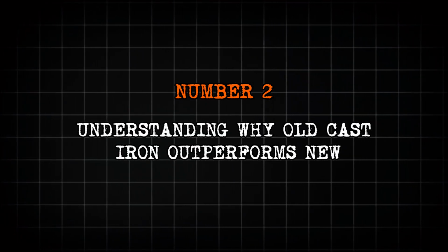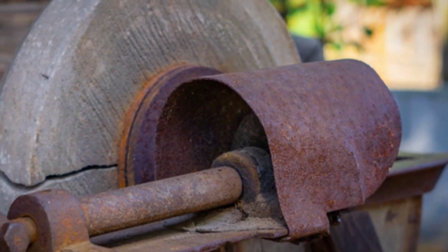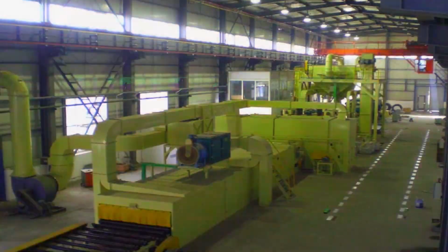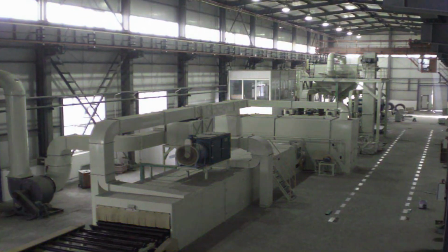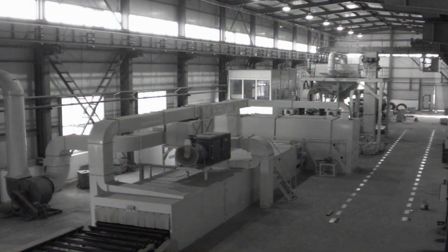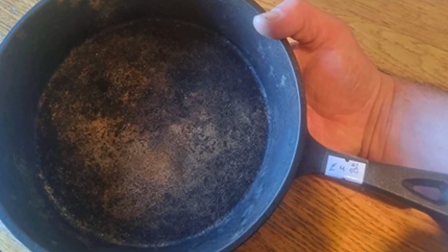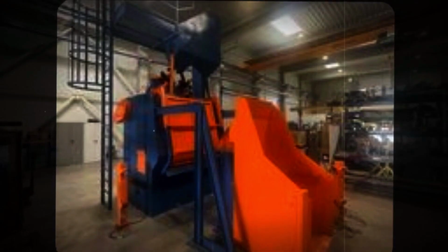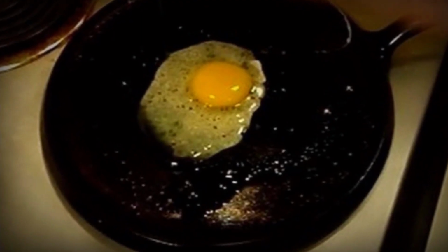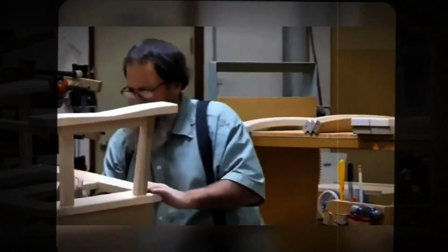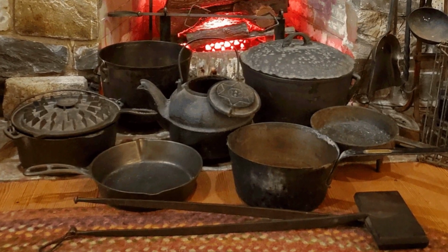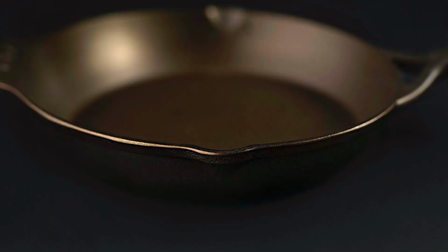Here is a truth that the cast iron cookware industry would rather you did not think too hard about. A 100-year-old Amish skillet outperforms a brand new cast iron pan of identical design in almost every cooking parameter, and the reason is not the quality of the iron itself. Older cast iron, particularly pieces manufactured before the 1950s, was polished to a smoother surface finish than most modern cast iron, which is typically left with a rougher, pebbly texture from the sand casting process.